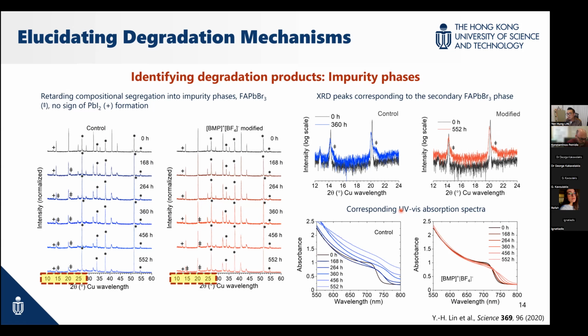But there's one thing, the halide might segregate. So what we see here is the phase formation, secondary phase formation. And from UV-Vis data, when we see this kind of control film, initially at 0 hours is very sharp absorption, but we can see it's redshifted.